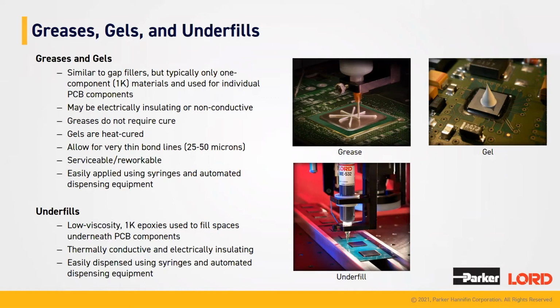One of the benefits that these have over some things like gap fillers, though, is that greases and gels, because of the filler particle size in each type of product, allow for very, very thin bond lines. And the thinner the bond line, that means the faster the heat transfer. So this is a big selling point for individual component thermal management because you want to transfer the heat out of those individual components as quickly as possible.